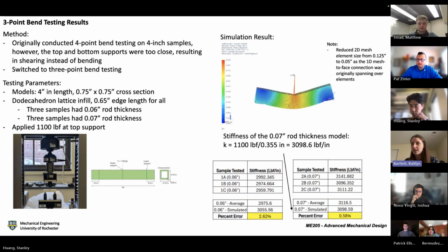I had to do a lot of figuring out the mesh density, the mesh element size. Originally it was 0.125 inches, but it was really interesting because it was spanning over elements that shouldn't have been in the mesh. So I reduced it to 0.05 inches, and that improved drastically. Then we got the stiffness to be 2.62% error between what we simulated and what we actually tested. And this was for the 4-inch models that had the dodecahedron lattice, because that's the lattice that we were focusing on.